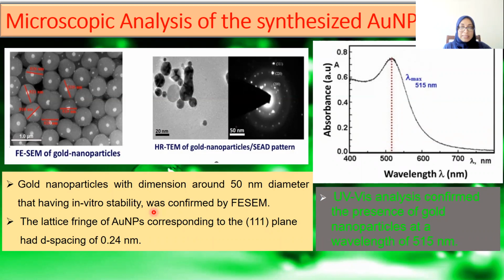Microscopic analysis of the synthesized gold nanoparticle. Here the gold nanoparticles with dimensions of around 50 nanometers and having in vitro stability were confirmed by the FESEM images. The morphology and crystalline nature of the gold nanoparticles were confirmed by the HRTEM images. And this is the UV visible analysis, which confirmed the presence of gold nanoparticles at a wavelength of 515 nanometers.